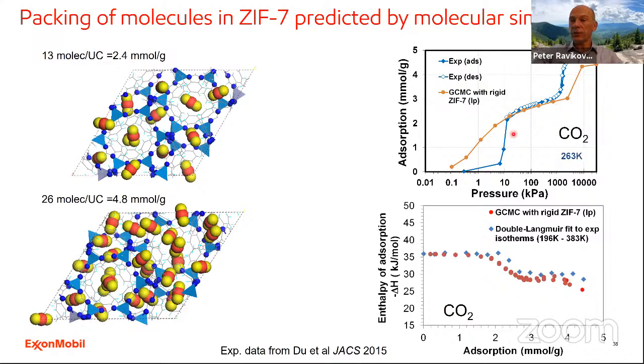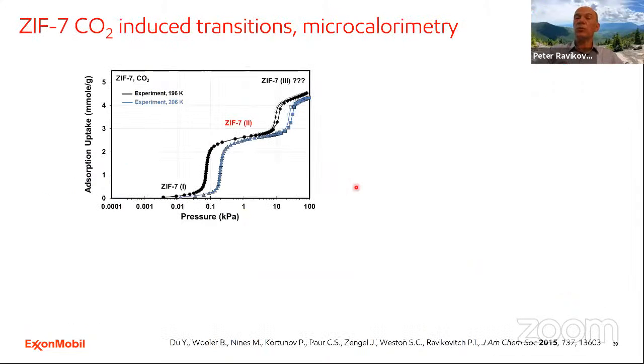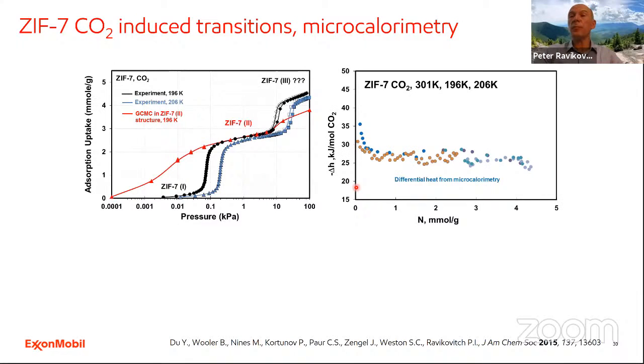And these are the enthalpies as predicted from molecular simulation in a rigid large pore structure of ZIF-7, in comparison with the enthalpies we obtained just by fitting the double Langmuir isotherms. So as you can see, this material has two types of sites, if you wish. It has high energy and lower energy sites. And you can do calorimetry. So we did a simultaneous adsorption microcalorimetry experiment in which we measured the enthalpy of this process.